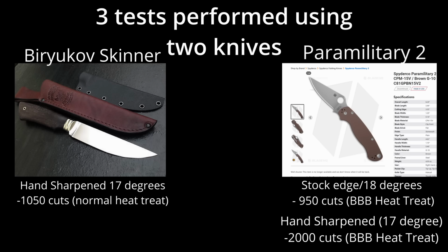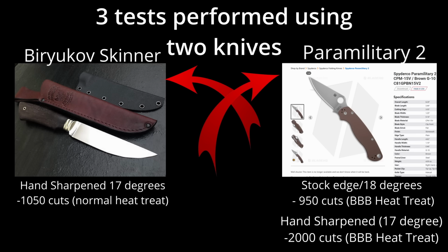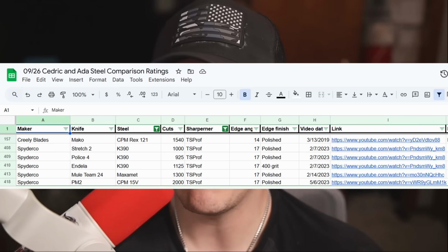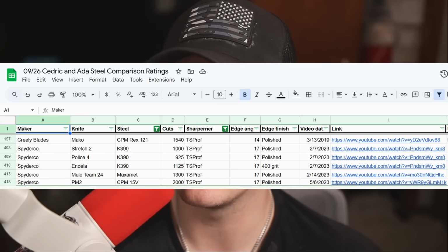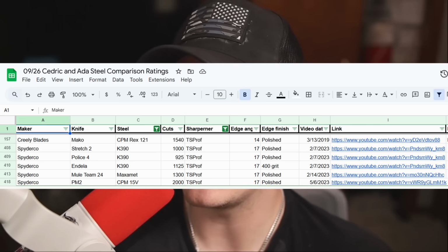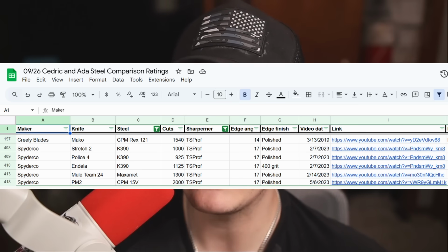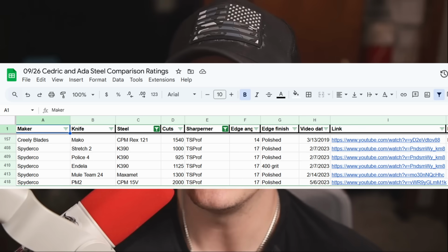Without a shadow of a doubt, this highlights the very undeniable advantage that the Big Brown Bear heat treat protocol provides when you're comparing the standard 15V knife against the Spyderco with the same edge angle but nearly twice the performance. And if you're interested in knowing just how impressive this really is, consider the prior reigning edge retention champion in Rex 121, who achieved over 1,500 cuts, or the runner-up in Maxamet with the same hand-sharpened and polished 17-degree edge achieving 1,300 cuts. Or how about K390 with the same geometry on its best day that never capped out higher than 1,100 cuts. Regardless of what steel you put up against it on this datasheet, the Big Brown Bear 15V has reigned supreme. So it should all be hunky-dory, right?